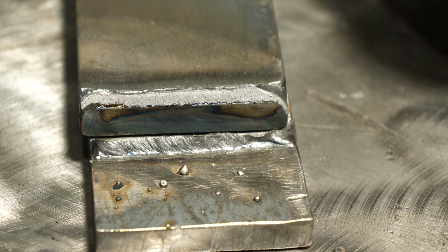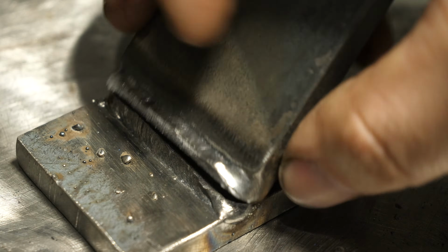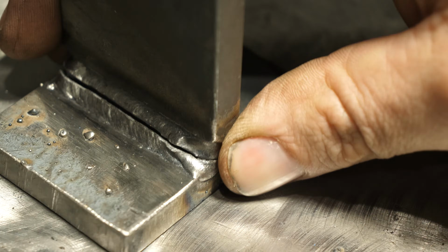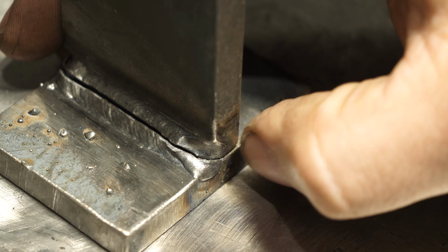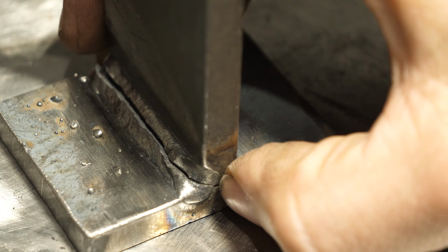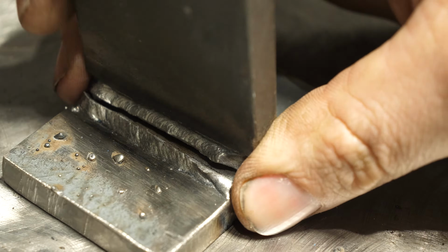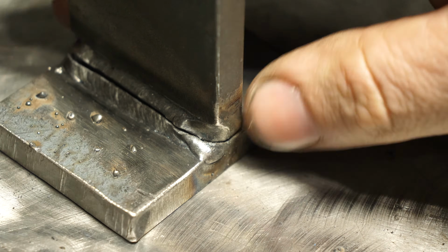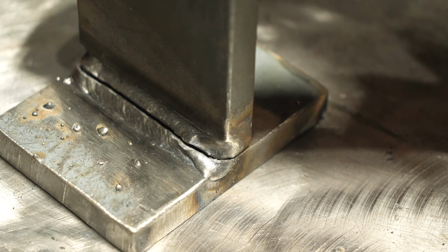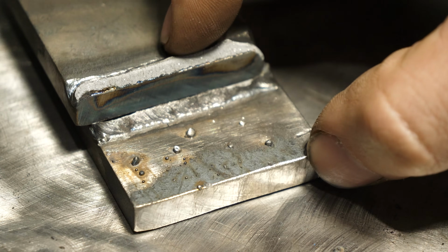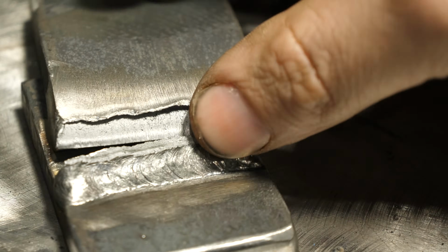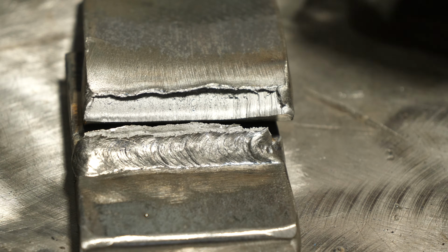Which, speaking of that, when you look here, the corner isn't really filled that well, and it did fuse down to the edge of the plate, same thing with the start, but if that was even a little bit better, this weld would have performed better. So this ultimately was a little weak. Pretty expected. Let's look at where I broke away from the face on this guy.